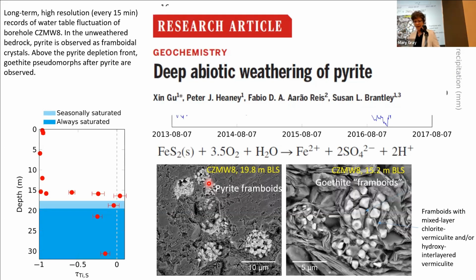But when we looked at the samples here, the shale down here has a very small amount of pyrite. When pyrite oxidizes, it produces sulfuric acid, so it'll dissolve a little bit of carbonate. But we're not talking about a lot of dissolution, or a lot of porosity development from the pyrite. And the rock is so tight, it has such tiny pores. We measured the pores with neutron scattering and other techniques. They're only about 2 to 10 nanometers.